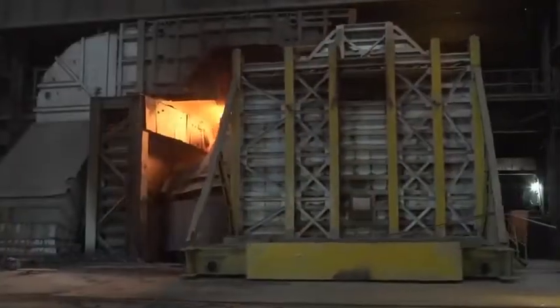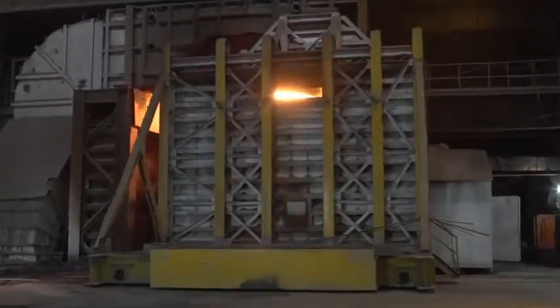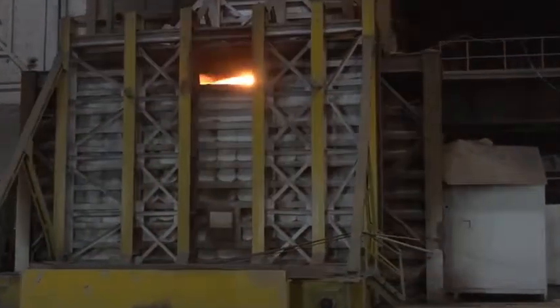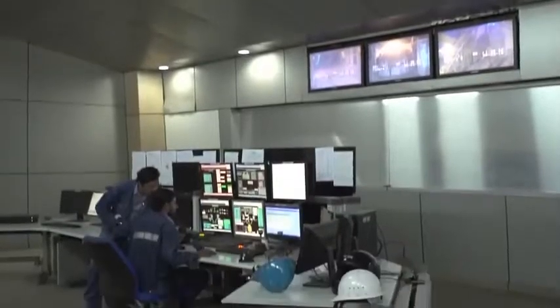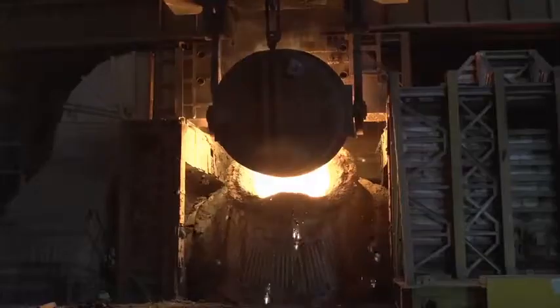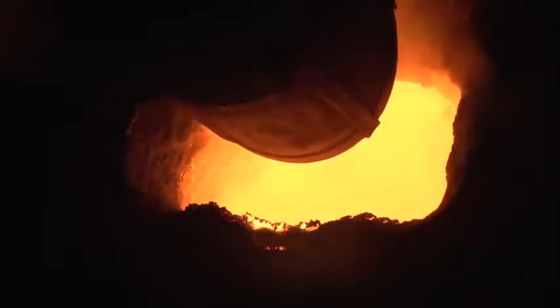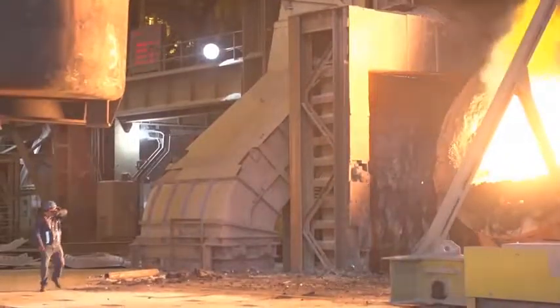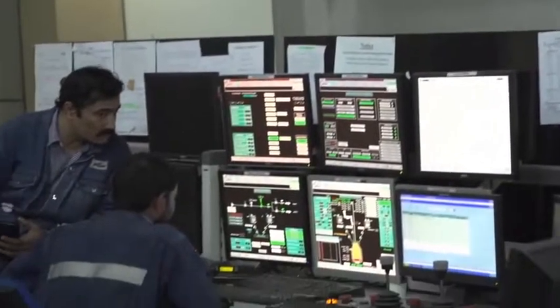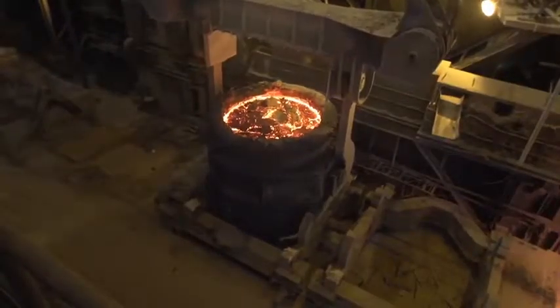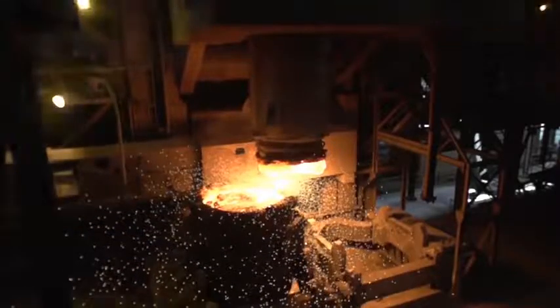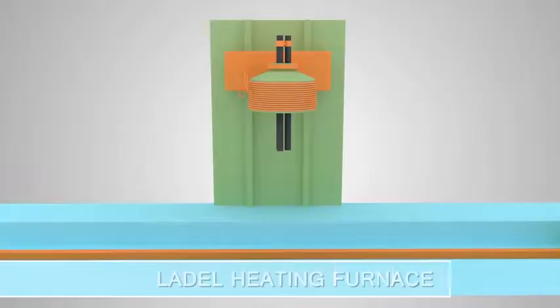The basic oxygen furnace shop has 7 converters in 2 separate shops, SMS1 and SMS2. SMS1 has a heat size of 135 tons with 3 converters, and SMS2 has a heat size of 180 tons with 4 converters, and the tap-to-tap time is 45 to 50 minutes. After passing through the converter process, the metal is then taken to the ladle heating furnace.